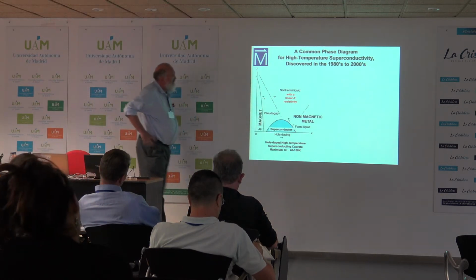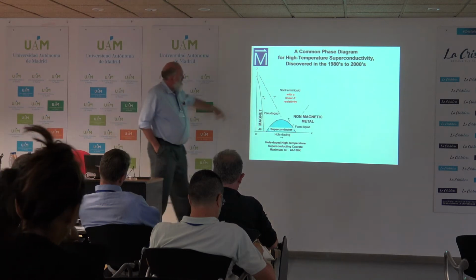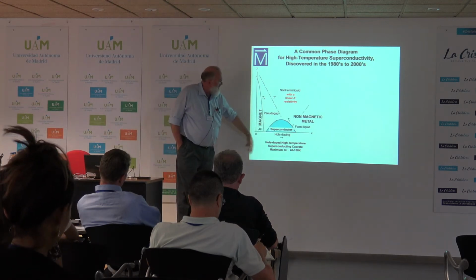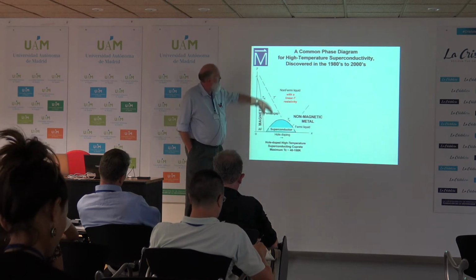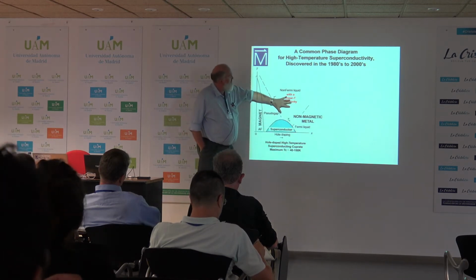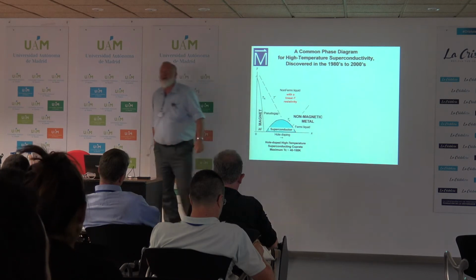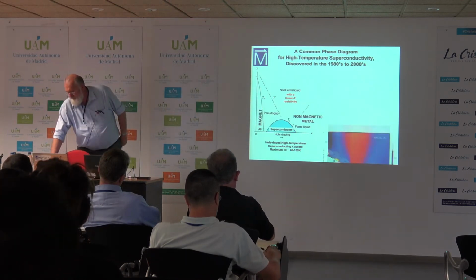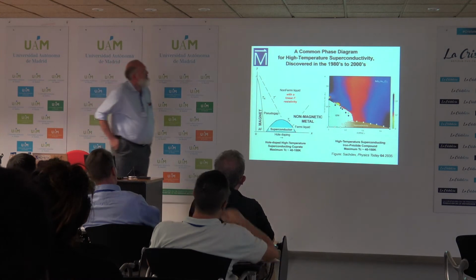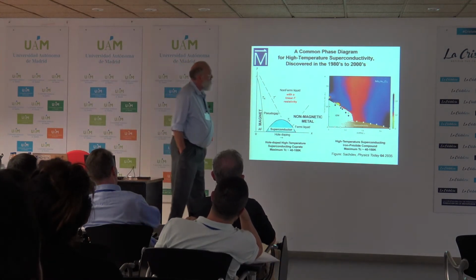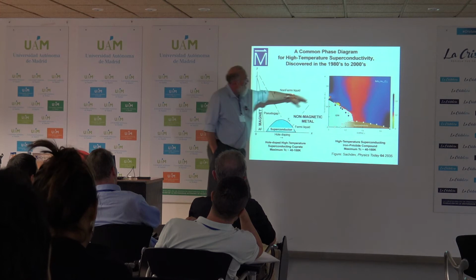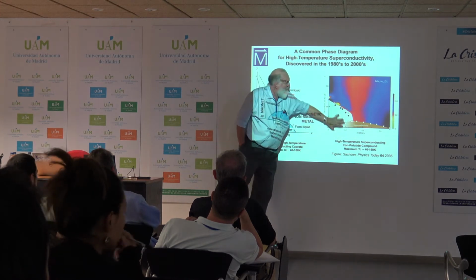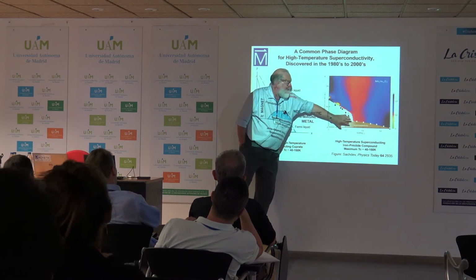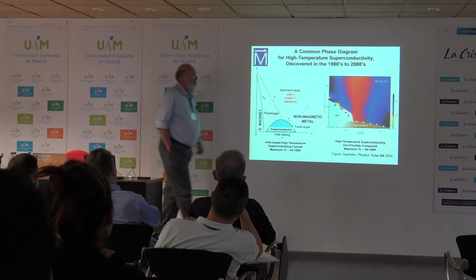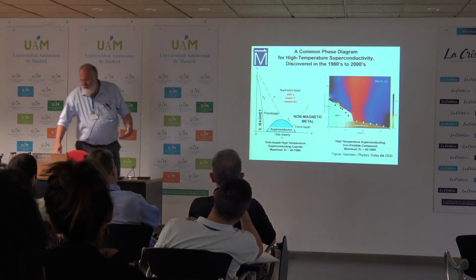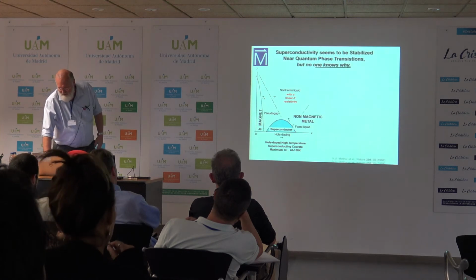So this is the simplified phase diagram for cuprates, hole-doped cuprates with TCs from 40 to 150 Kelvin, the mercury compound under pressure, and they have this linear T resistivity that Tony presented. And here's the barium-122 compound that we'll be studying, where the magnetism actually comes out all the way over to optimum doping. And we know that we have a transition from spin density wave to a non-magnetic phase near optimum doping. And so we'll be looking for critical behavior in that regime.